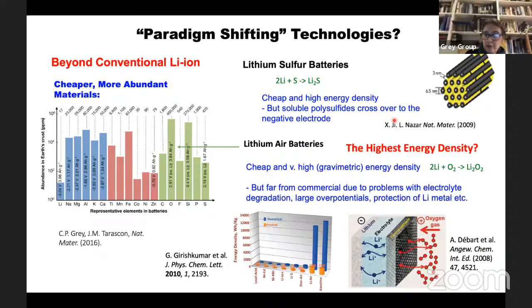So what are the real paradigm shift changing technologies that could really make an impact? If we really want to look at those, we want to go to really cheap elements. So we look at sulfur, we look at oxygen, and we could do a lithium sulfur battery, which is a reaction of lithium and sulfur to form Li2S. The problem with that, and this is basic inorganic chemistry, is that to go to Li2S, you go from S0 to S2 minus, and you go via these polysulfides. Sulfur is a ring, it's got S-S bonds, it's S8, but you've got a slew of compounds in between, like S2 2 minus, and the 3 members things, and they're all soluble. So they dissolve in the electrolyte and you end up with redox shuttle processes. And so it's very challenging to get that to work.